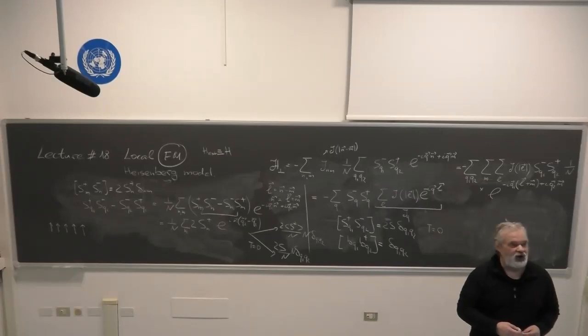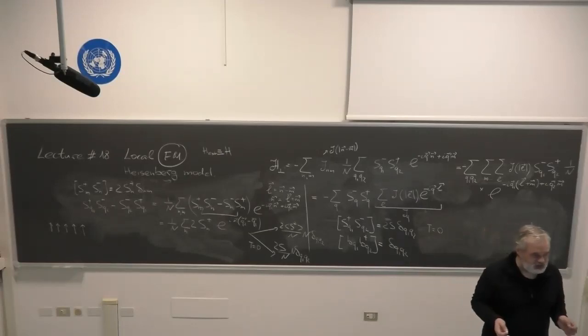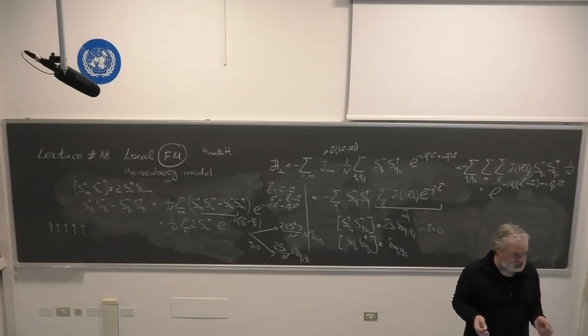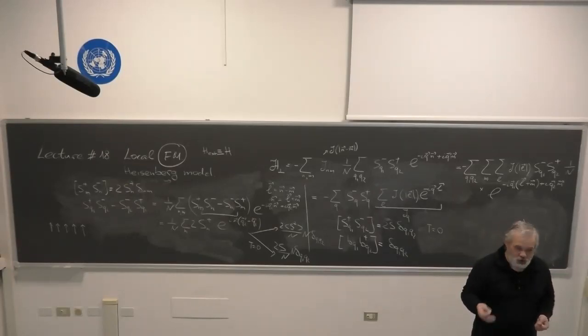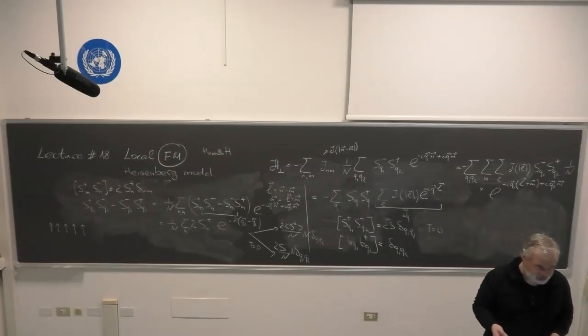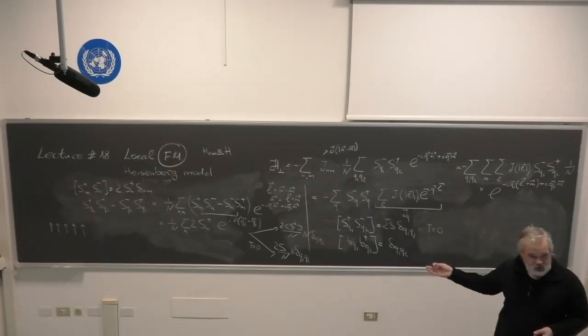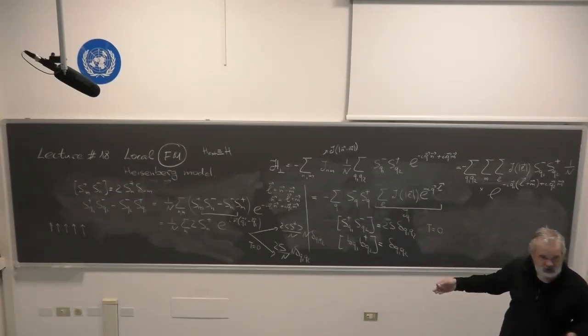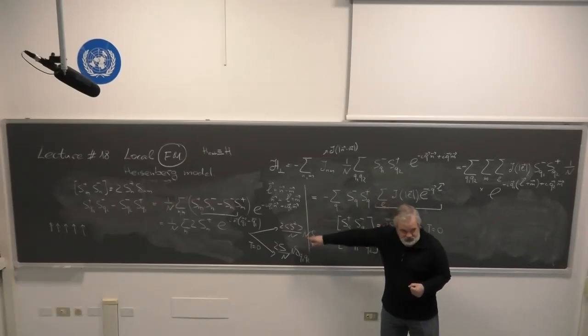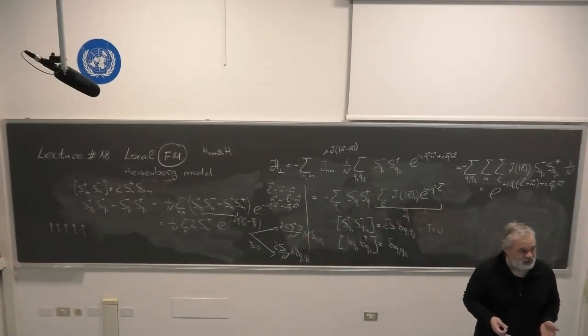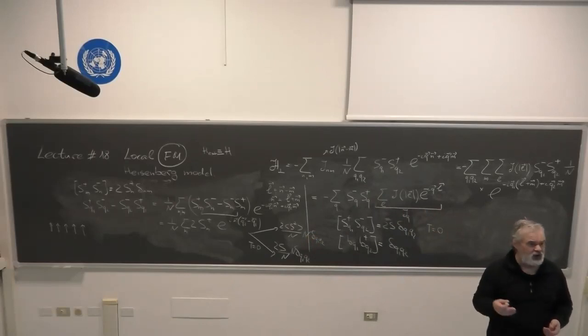It's all a trick. As I said, the problem is that spins in general are neither fermions nor bosons. Therefore, whatever representation in terms of fermions or bosons you use, this representation will not be fully correct. There is a price which you are going to pay. In particular, when I introduce the bosonic representation of the transverse component, the price which I pay is the non-exactness of this relation at finite temperature. Equally, I can use a fermionic representation. I can express spins in terms of Majorana fermions or whatever.